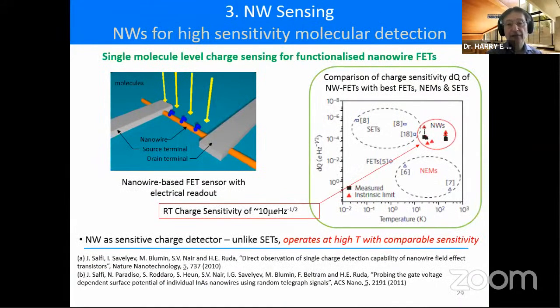And this is taken from a paper we put out in Nature a while ago. What you can see is that you can establish a charge sensitivity for such nanowires. So we can use those fluctuations to measure charge. Right? And on the left-hand axis of the figure on the right, you see the charge sensitivity in units of electrons per root hertz. And the best sensors for charge are single electron transistors, which operate at helium temperatures. And they have sensitivities which are under an order of magnitude better than our wires. But the difference is our wires are running at room temperature.